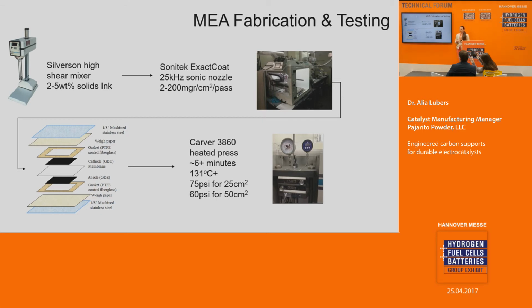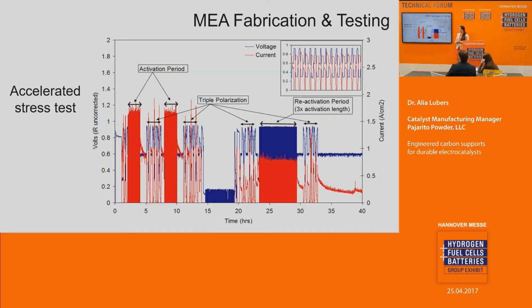In order to evaluate if it's a good support or if it's a good catalyst, we have also started to produce MEAs for evaluation. How we do that is use a high shear mixer for producing inks. We have a sprayer to produce gas diffusion electrodes. And we use a heated press to produce a 7-layer MEA. We also use a DOE-recommended accelerated stress test to mostly evaluate carbon corrosion. So the graphs that I will show you will apply this type of accelerated stress test.